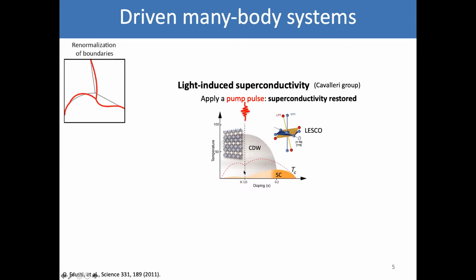And so in equilibrium, you don't expect to see any superconducting behavior. And what they did was to apply a pump pulse. So basically drive the system, shine light on the sample. And to their surprise, they were able to see transient superconducting behavior. So in a way, you basically increase the region of stability of your superconducting order. So this is an example of phase boundary renormalization.